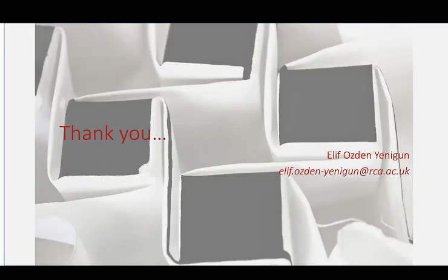So you also mentioned the layers of accumulation on the surface, not to make a rigid body on a soft material. The question is very related to that. Is it the material property you are dealing with when you try to make these conductive lines on a very rough surface? Or is it just a matter of accumulation, because you have to make this percolation to have a good conductivity, and the material moves, it's a soft material, especially when you stretch a fabric. How do you tackle this challenge? How do you manage to keep the high conductivity with the movement of the fabric? Even if it doesn't move, it's just making this percolation network on a very rough surface.